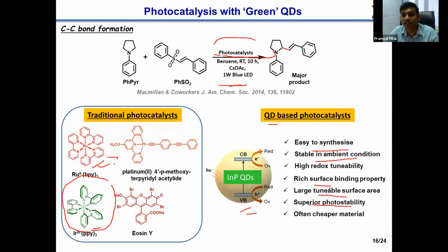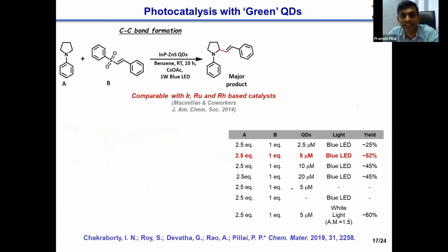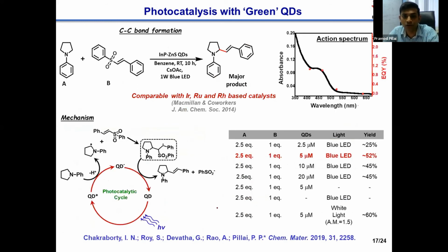So this is the reason why we wanted to test whether these materials can be used as an efficient catalyst, and this is the result. And we found that our quantum dots are equally good as these traditional catalysts. So we are not claiming that they are better, but what we are claiming is they are equally good as the traditional catalyst. So this is the mechanism of the catalytic cycles.